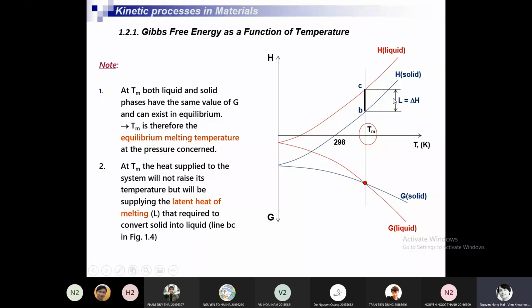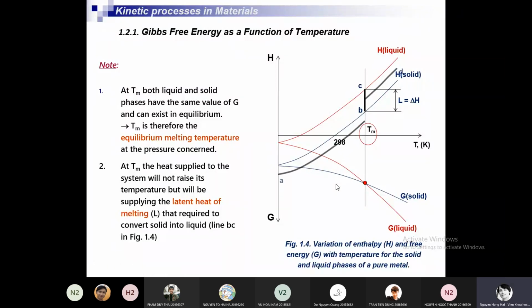So the latent heat of melting L is equal to the difference in enthalpy between liquid and solid state. You see in this graph, you can see the latent heat as the difference in enthalpy between liquid and solid. If we have the solid and we supply heat, the enthalpy will increase by interval AB from room temperature to the equilibrium melting temperature.